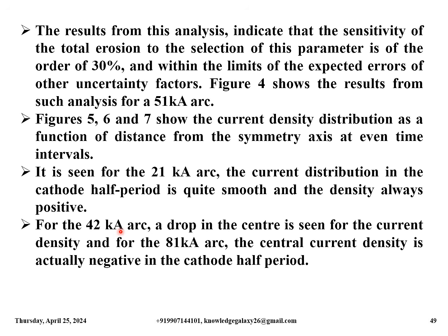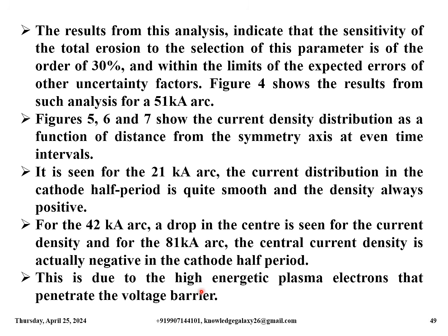For the 42 kA arc, a drop in the center is seen for the current density, and for the 81 kA arc, the central current density is actually negative in the cathode half period. I am just explaining what I had earlier mentioned during the figures' depiction. This is due to the high energetic plasma electrons that penetrate the voltage barrier.